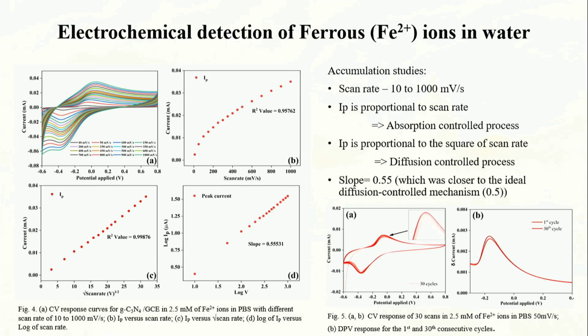At higher concentration, we need this to be a diffusion control process in order to show the previous phenomena. So we plotted the logarithm of the oxidation peak current against the logarithm of the scan rate, and we found that the slope is 0.55, which is close to the ideal diffusion control mechanism, which is 0.5.